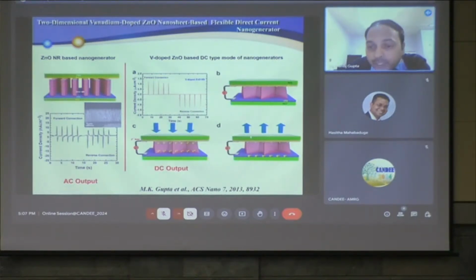Now once we release the pressure, it should be a negative pulse here, but it is not coming. It is coming in a DC kind of nature. So why a DC kind of output voltage? Because once we apply the pressure, the electrons come to the bottom direction. But when we release the force, the electrons do not return to the top electrode, and then we miss this reverse peak, and only DC kind of nature is coming just because of the electrostatic field created by this vanadium atom.